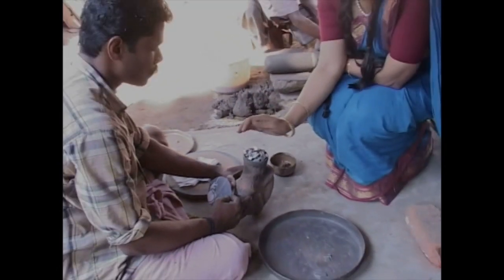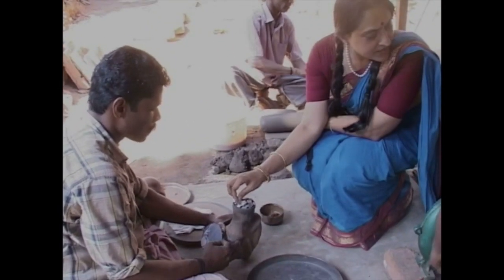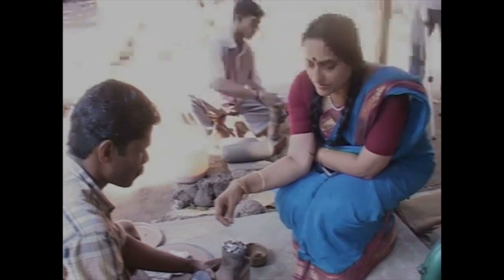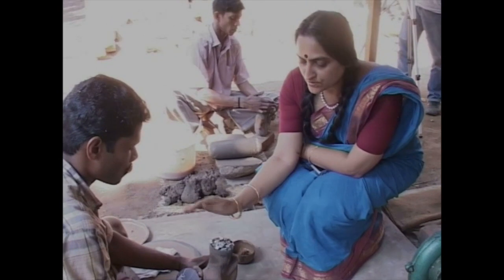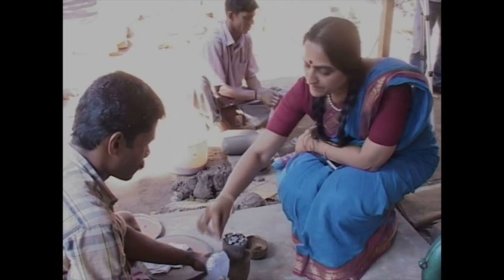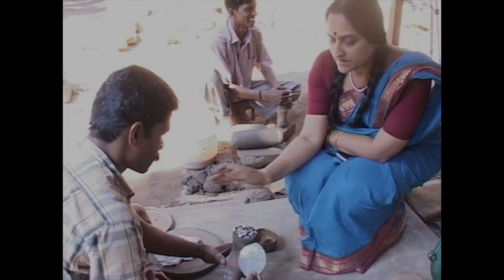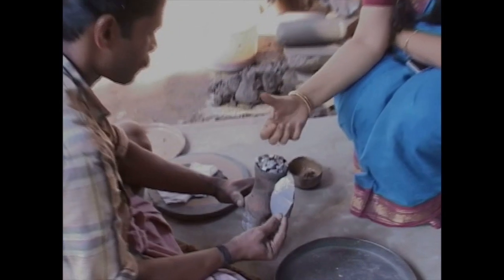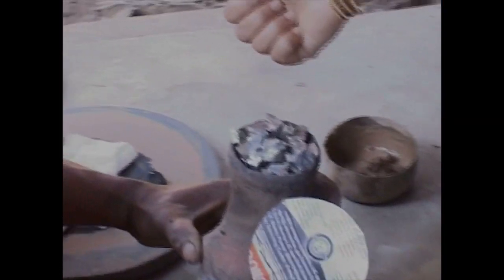This is the 33% bronze alloy, delta bronze alloy. It is to be cast in that thin line, as I mentioned, which will be polished and finished. So he fills the mouth of this with some mold, and then he seals it with cloth. First paper and then cloth, combustible materials, so that the gases can escape. Then he seals it so it flows through the mold.